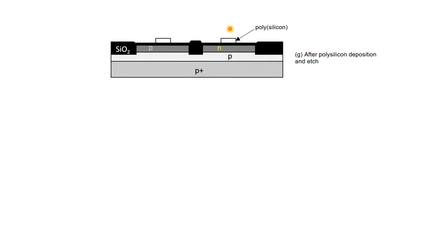Now if we implant the group 3 materials with a heavy dose, because the source and drain doping concentration has to be quite high, then what will happen? This is the channel region for this MOSFET. This channel region is now protected by this polysilicon. So one p plus region will form on this side of this gate. Similarly, one p plus layer will form beside this gate. These two will form the drain and source respectively.